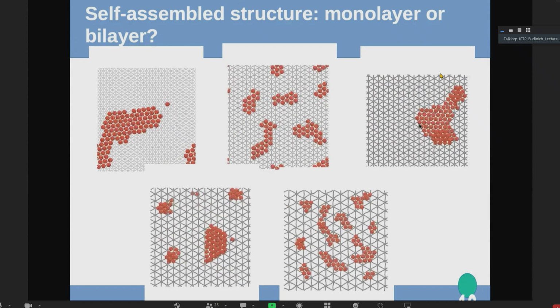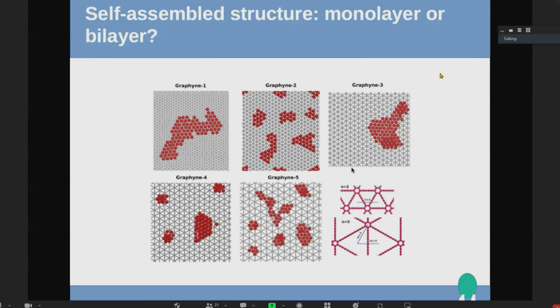More interestingly, it was a feature that we observed. If you look into the graphyne 3 structure, we have a bilayer rather than a monolayer structure. For this case, graphyne 3 and graphyne 4, for both cases, instead of creating a monolayer structure, it is a bilayer structure, since C60 is not going to attach to the boundary of the structure. It is more favorable for one C60 to jump on top of the first layer and create a bilayer structure. It might be more interesting for a specific application.